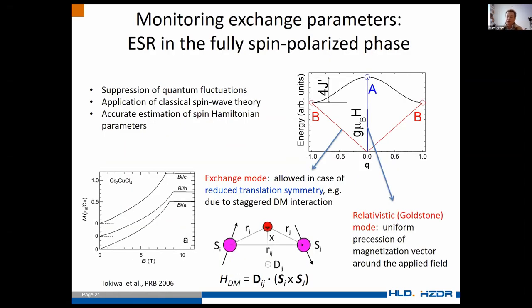First of all, why is this material very interesting? Looking at magnetic excitations at very high magnetic field, we can use classical spin wave theory and look at the dispersion of magnetic excitations. We can observe not only the transition at k equals zero, but also at k equals pi. The transition at k equals pi is allowed because of a staggered Dzyaloshinskii-Moriya interaction. The translational symmetry is reduced, the wave functions get mixed, and as a result we can observe this transition. This is not often the case, but here we can see transitions at k equals zero and k equals pi, corresponding to the relativistic mode and the exchange mode.